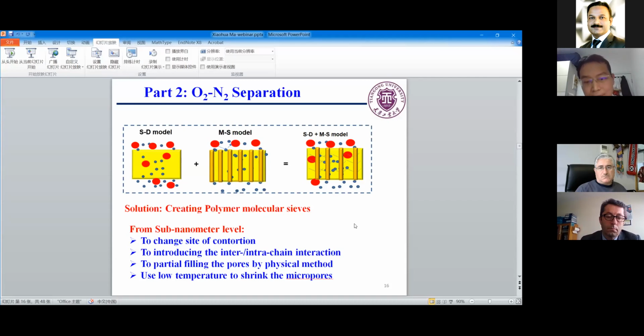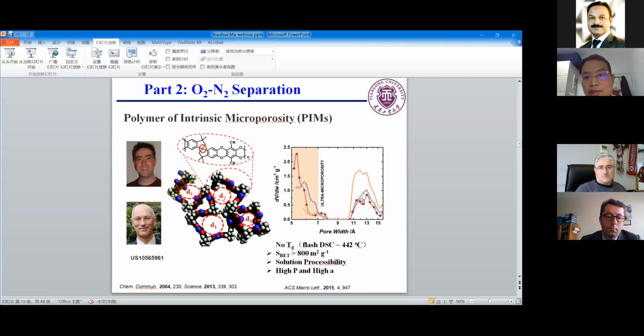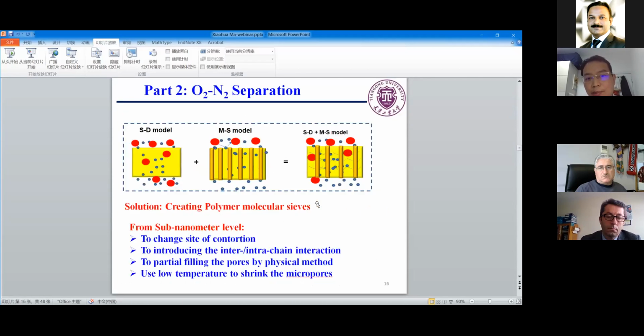In my group, during several years of research in this field, I think we have many methods to engineer the pores at sub-nanometer scale. In this case, we know the pore size distribution. We can decrease the nanometer pores and keep most of the ultra-micropores. Because these ultra-micropores are in the range of the kinetic diameters of the gas molecules, we can get membranes with both high permeability and selectivity.